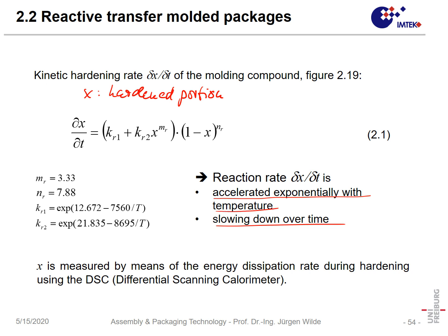And typically here we have such factors which are proportional to e to the power of some activation energy divided by temperature. So that's a typical Arrhenius equation. And you could say if you have something which involves chemistry, and when you regard temperature dependency, in most cases it is correct to use something like the Arrhenius equation in order to describe how the reaction rate increases with temperature.